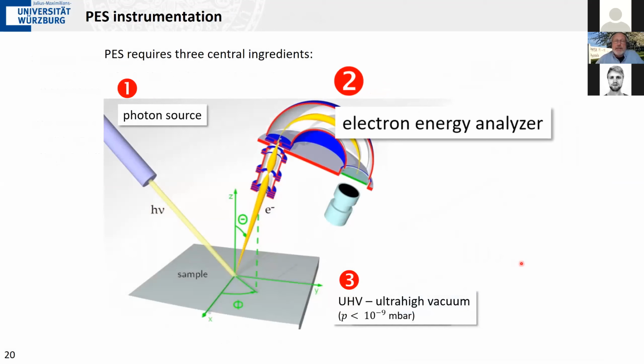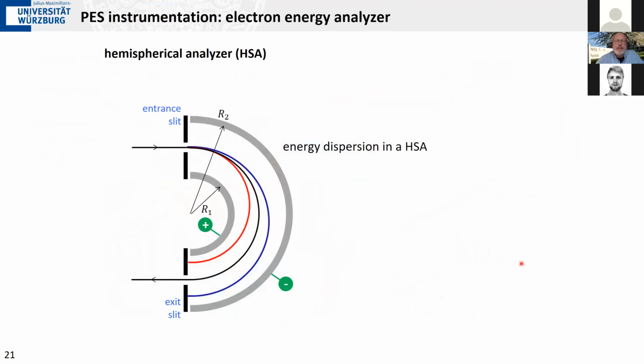Okay, so for the light, now we need to detect the electrons. And we have to measure the electron kinetic energy, and you do this with an electron energy analyzer. And what we use here typically is a hemispherical analyzer. So that's basically, you can think of it as a capacitor that depends on an inner sphere and an outer sphere, and you apply a certain voltage between them, and you create by that an electrical field. That's basically a Coulomb field. It's a 1/r field in there, and all electrons that get into this field will propagate on Kepler ellipses.